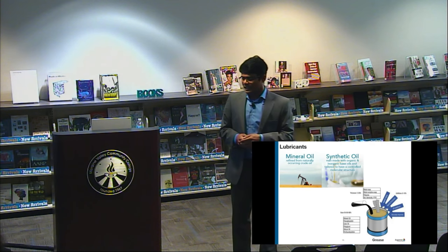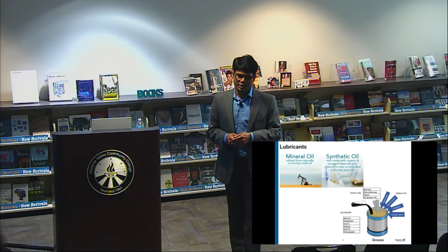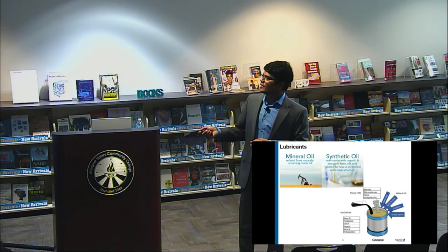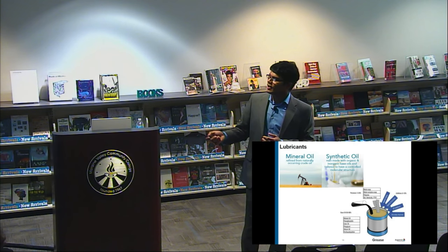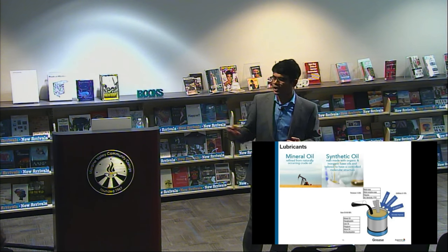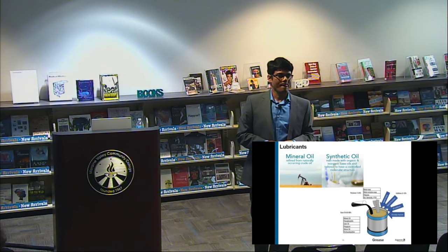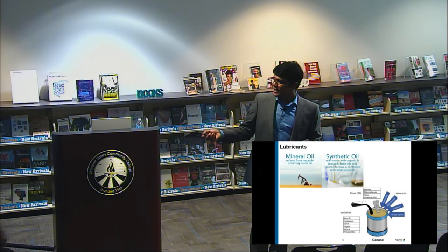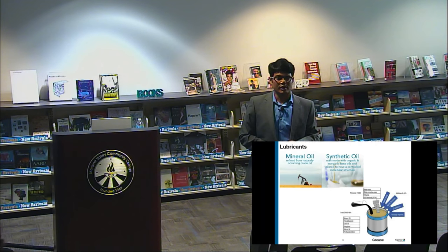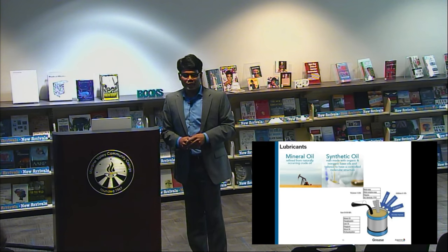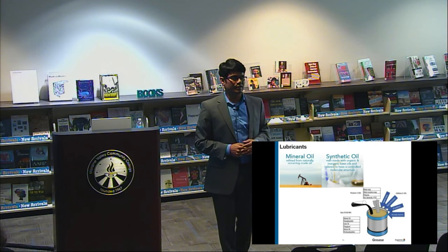And oftentimes, when you see 5W-20 or whatever oil is changed in your car, that is actually a synthetic oil with additives. The oil cannot sufficiently provide every protection on its own. So we develop additives like anti-wear, anti-corrosion, EP additives and viscosity improvers. And when it comes to greases, we add a thickener to the oils with the additives. That makes it a semi-solid kind of material, which is grease. It is used mostly when access to the intricate part is very complicated and you cannot really provide continuous lubricant at the interface.